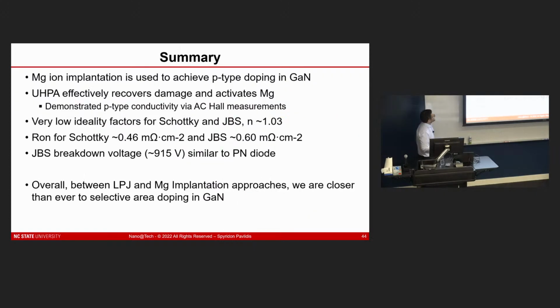So I'll wrap up here to make sure that there's a few minutes for questions. But basically what I'm demonstrating here is our ability to use magnesium implantation in conjunction with ultra-high pressure annealing to achieve p-type doping in GaN. We use that UHPA approach to recover damage and activate the magnesium. And through Hall measurements, we can show that we have high p-type conductivity on par with epi material. And these low ideality factors that we're showing now are very, very promising. We have really tuned this process a lot, and we're able to get good contacts and good behavior from these devices with low resistances that come from that as well, which are really record-breaking compared to what was published up until now.